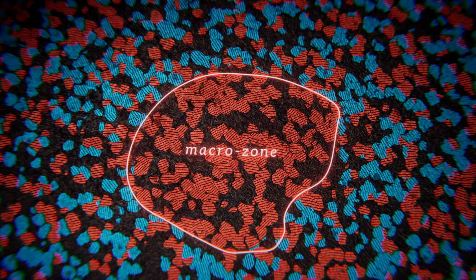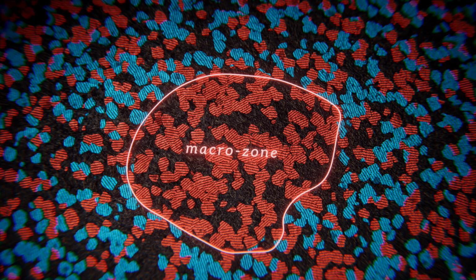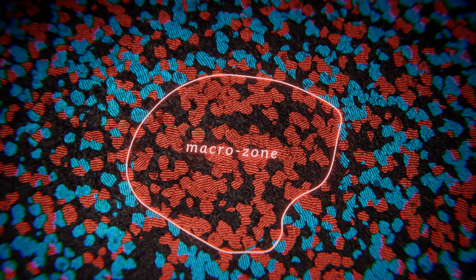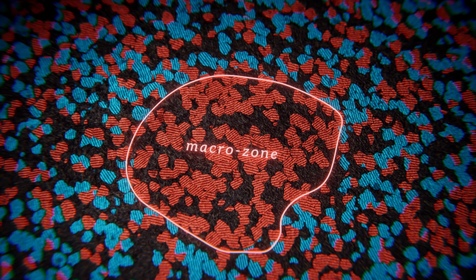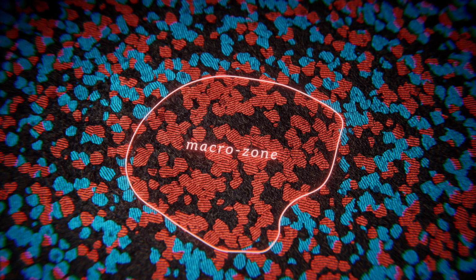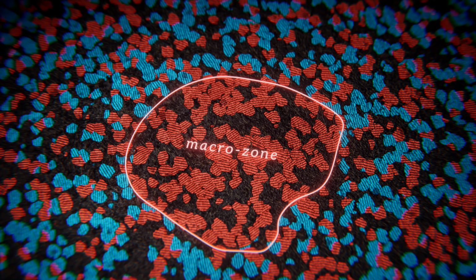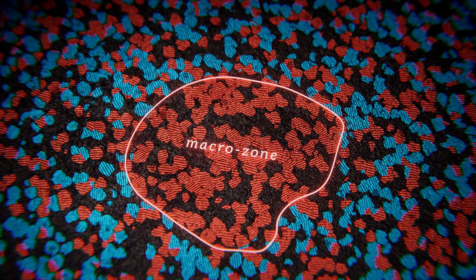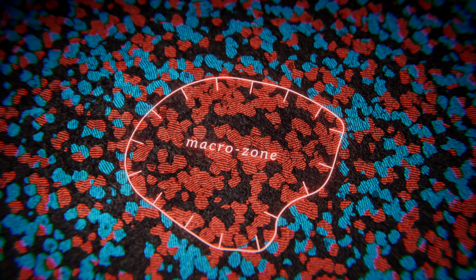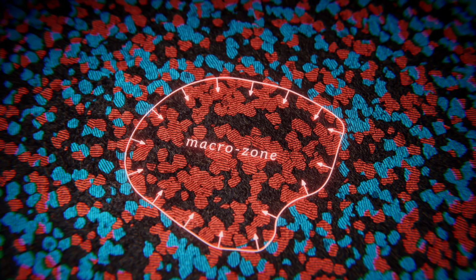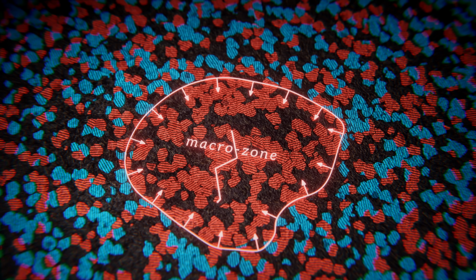A cluster of grains that's hard relative to the load direction doesn't contain any soft grains within it to redistribute the applied stress. Under prolonged dwell loading, the softer surrounding material continues to deform, transferring more and more load into the hard region, and creating a stress concentration that can cause cracking to initiate.